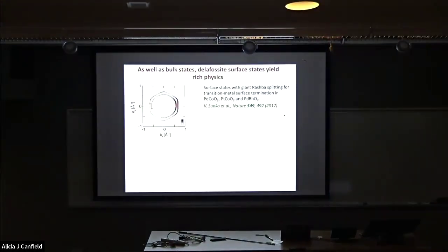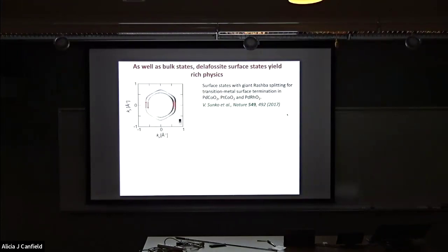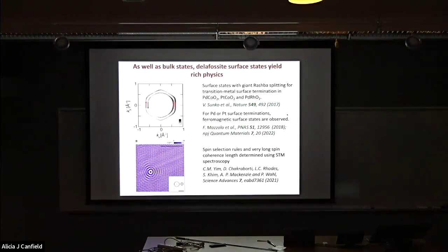But within about 50 months of starting her PhD, she made the measurements, came up with the answer, which I'm not going to give you today because I don't have time to talk through it all, but I can do it in private. Made a model, made a prediction, took new data on palladium rhodate, which confirmed her prediction. And you know, if we could all do work of that quality, I'd be extremely happy. So there's some very interesting surface physics. There's also ferromagnetic surface states when you terminate with the palladium or platinum. So there's definitely quite a lot of interest in the surface of these materials these days.